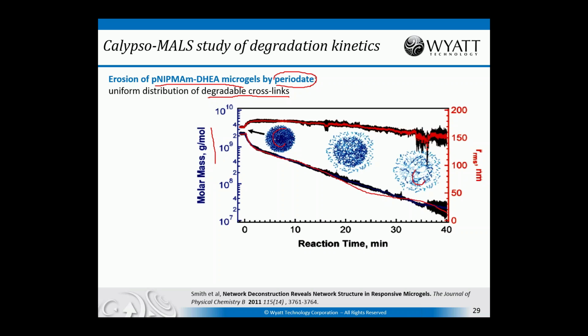What else do we see? Well, we also have a measurement of the size of the particle, the root mean square radius determined by multi-angle light scattering. And interestingly enough, at the beginning, actually the root mean square radius increases, and then there's a relatively small change over the course of time. And so that's a little bit curious.